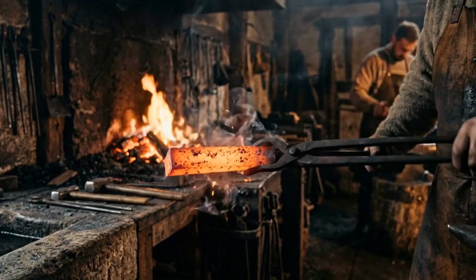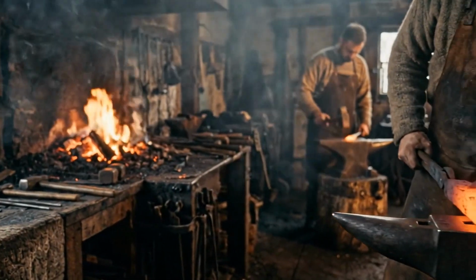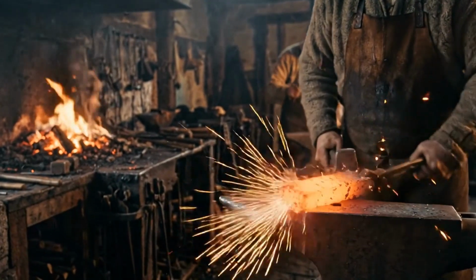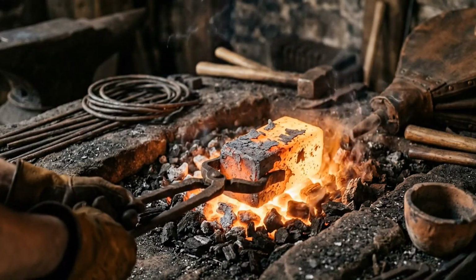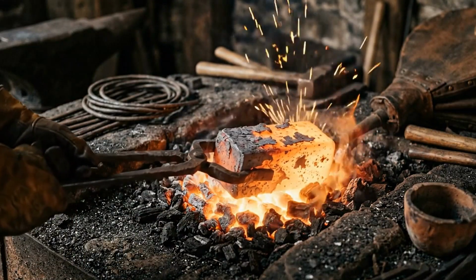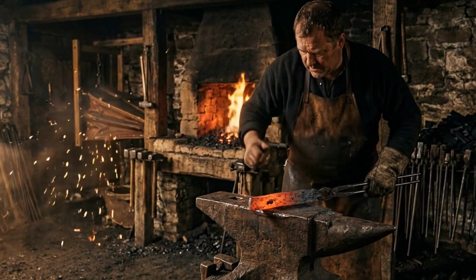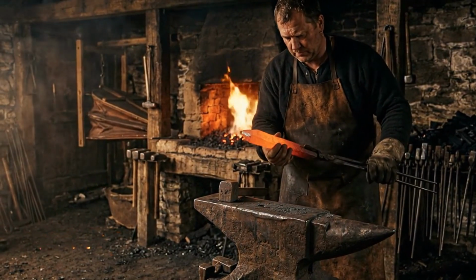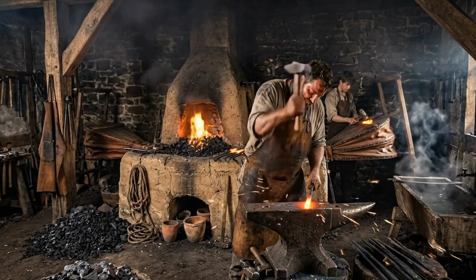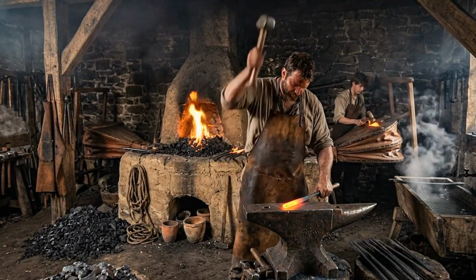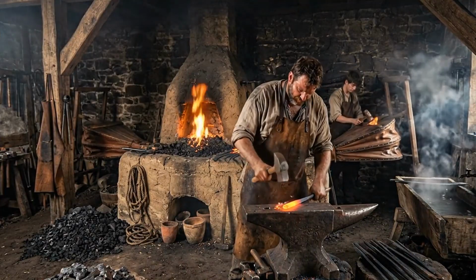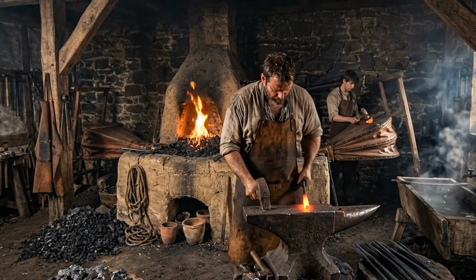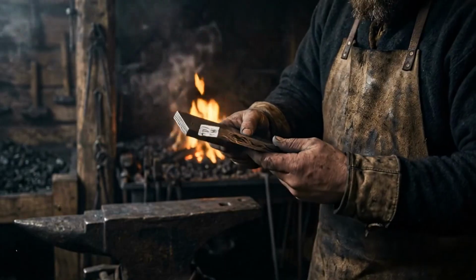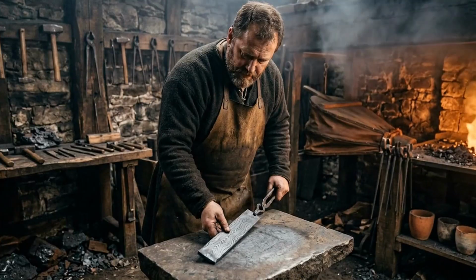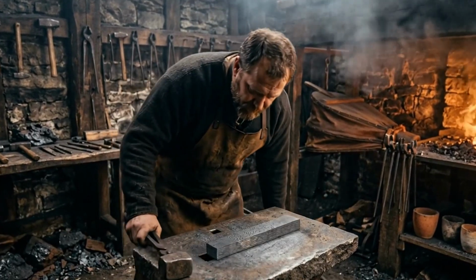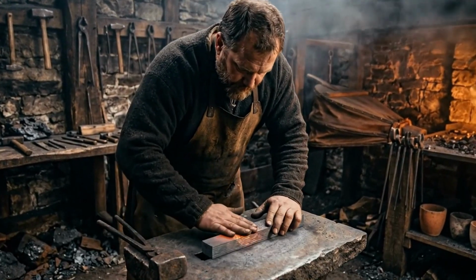Beyond a certain number of folds, the carbon content of the steel began to drop as the repeated oxidation of the surface during each heating cycle burned off carbon into the atmosphere. A smith who folded too many times would end up with soft, low-carbon steel, a blade that would bend rather than hold an edge. The number of folds was therefore a calculated decision, not a formula. Different schools of swordsmithing developed their own preferred counts, and the exact number was considered proprietary knowledge passed down within each tradition.